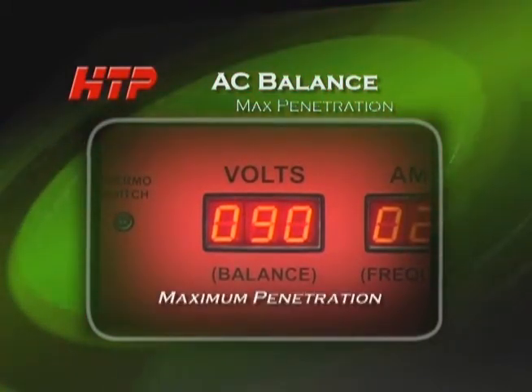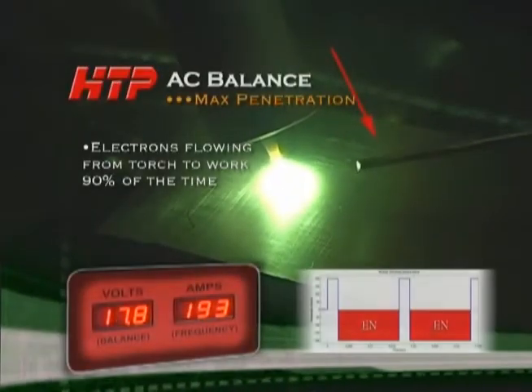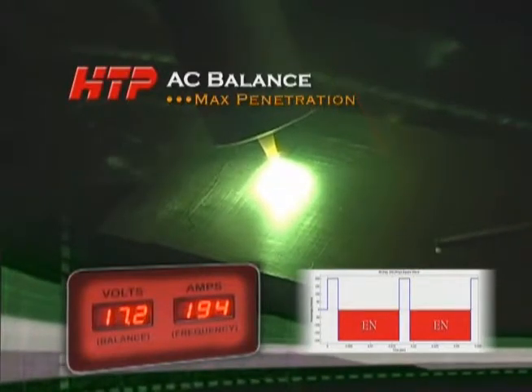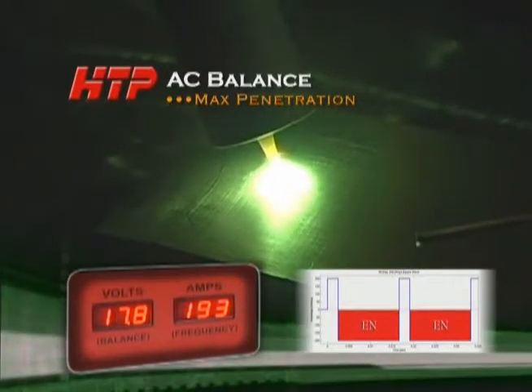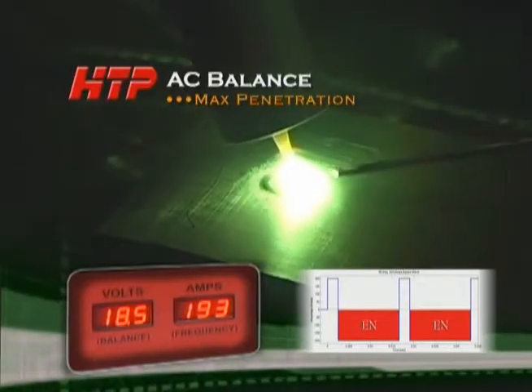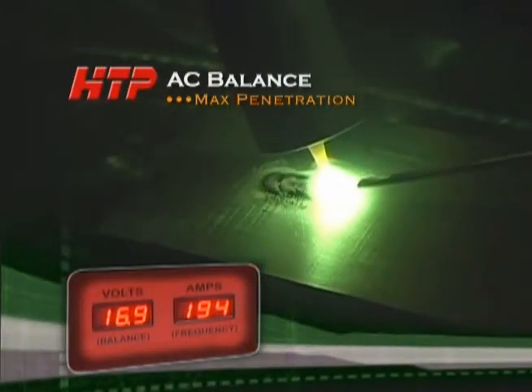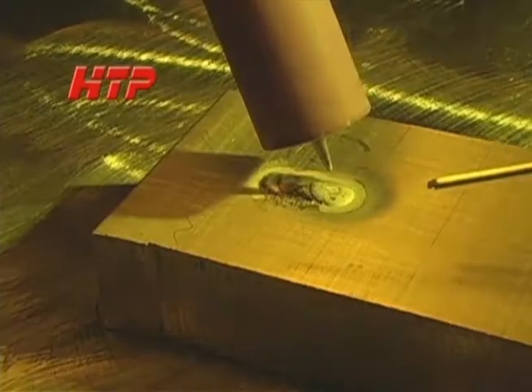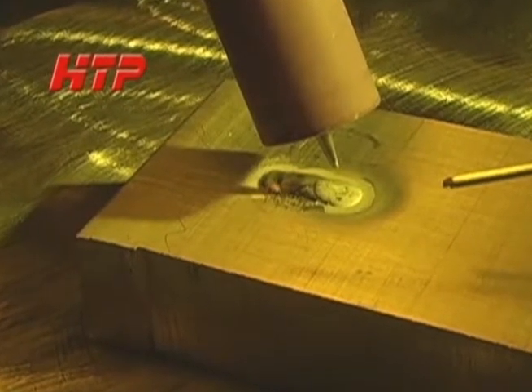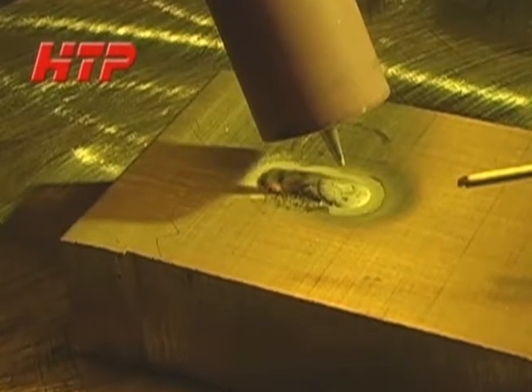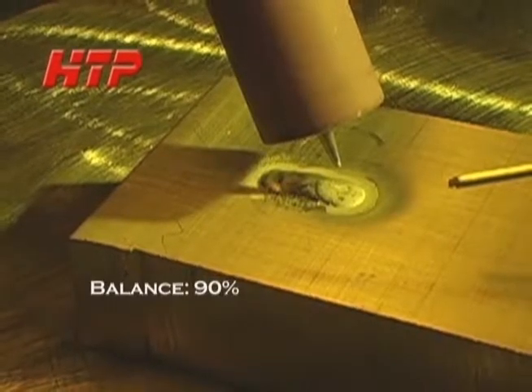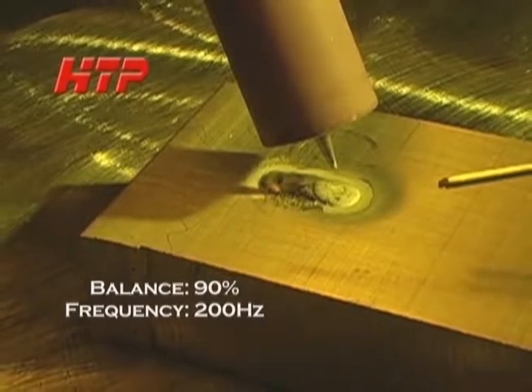With the balance set to maximum penetration, which in the case of the Invertig 201 is 90%, 90% of the time the electrons are flowing from the torch into the work and putting heat into the work, providing maximum penetration. This is a piece of 3/4 inch thick aluminum. Generally, with a 200 amp TIG welder, you would not be able to get a molten puddle to start a bead. But with the Invertig 201, you can see with the balance at 90%, frequency at 200 Hertz, we have enough heat to get a molten puddle and run a bead.